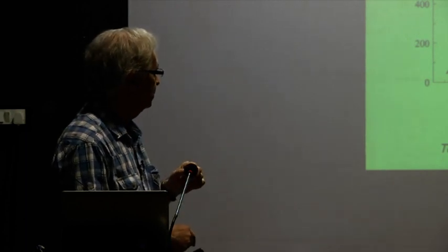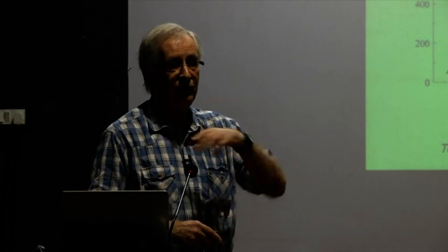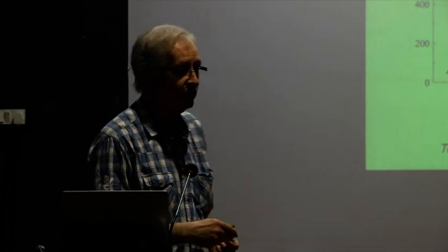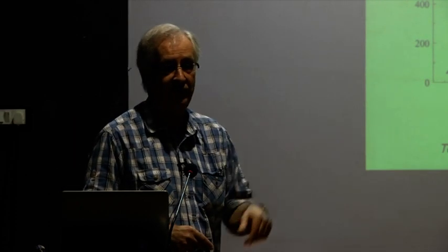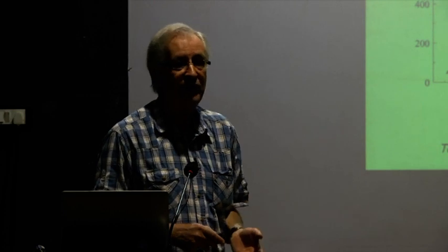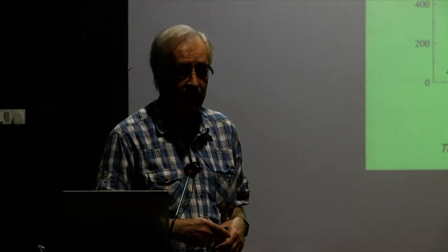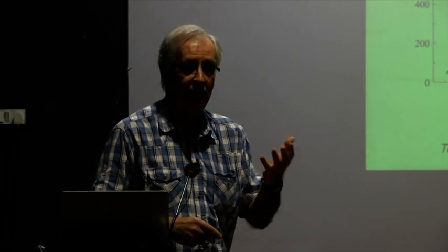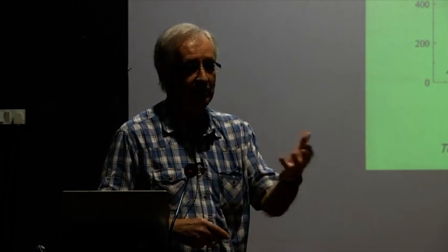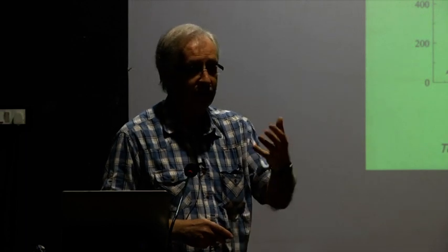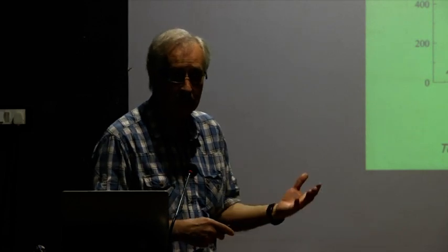And then you plot them out. You plot the martensitic transformation temperatures for a whole bunch of materials, all on one graph as a function of electron concentration. You don't care about the individual elements. You care about the number of electrons that they carry as valence electrons. And you do see a certain systematic, meaning that, of course, the valence electron concentration is an electronic property of a metal, and there should be some consistencies independent of what the species are.